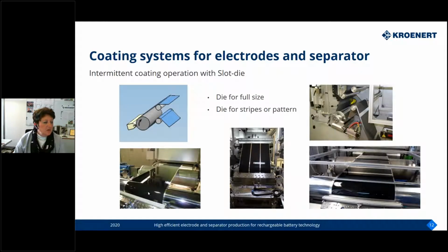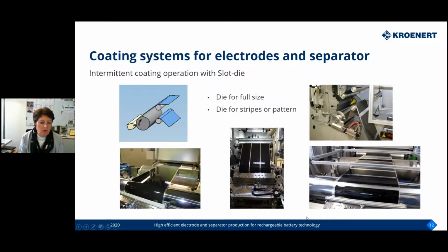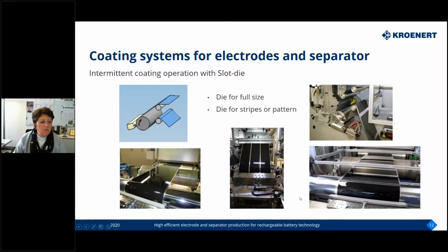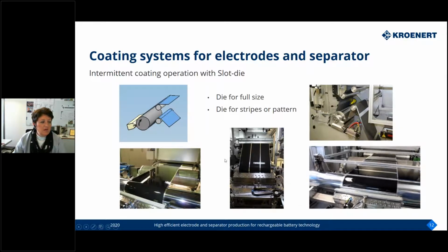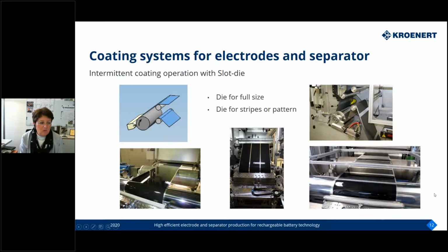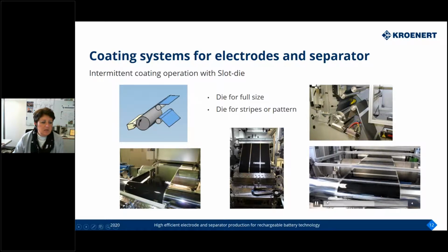The advantage of such slot die technology is that you can have it in a full range cover, so you can really adapt the system that you coat a closed layer without any stop. It's also possible with a special shim system inside the die to coat stripes. This is also quite reasonable. Mainly if you go to a wider working width, such intermittent coating technology, which you will see here in the short movie, will not work anymore. In that case, as soon as you go wider than 500 millimeter, 600 millimeter working width, we always explain or offer the stripe technology for such a design. And as soon as you go to a smaller working width, such intermittent coating systems can be realized with a special design of the slot die.